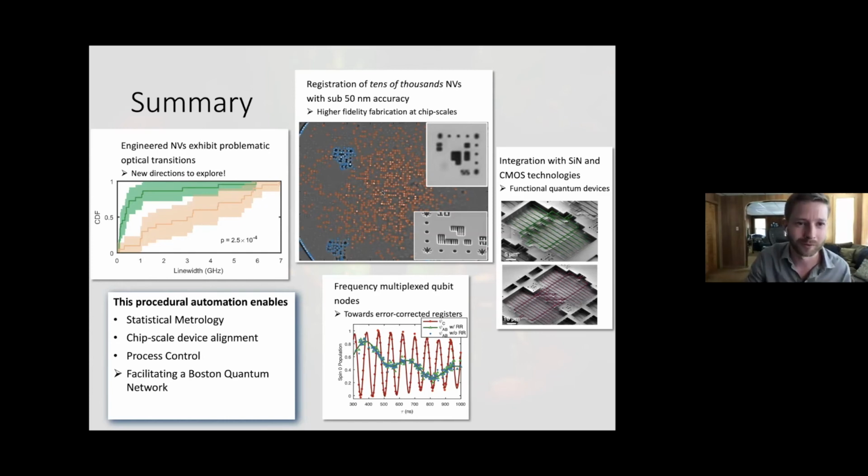But just another quick fact about these is that you'll see that it actually lines up in a pretty nice grid, which is something that is super nice about a silicon vacancy center, which we don't have the luxury of with a nitrogen vacancy center. Because nitrogen, apparently, I'm not an expert on this, doesn't have a focused ion beam source, whereas silicon and some of these other heavier elements do. So that is one example that I snuck in there.